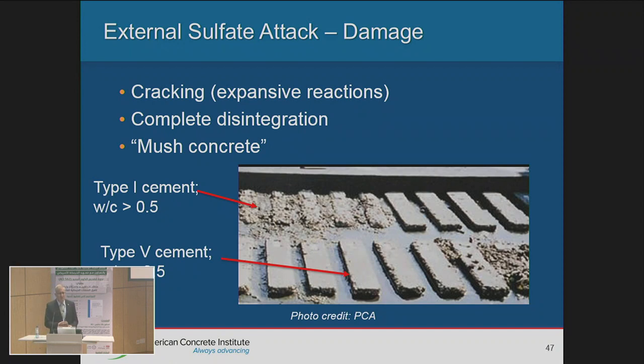Sulfate attack. There was a study that was done in California, Sacramento, where they took concrete samples. They designed them with different concrete types, from type 1 all the way to type 5, and also with different water cementitious ratios. And they placed them in a bed that is saturated with sulfate, and they left them for about 6 to 7 years and observed how the concrete would behave. And here, if you look, those were done with type 1 cement with a water cement ratio greater than 0.5. Nothing else, just left them in that bed.